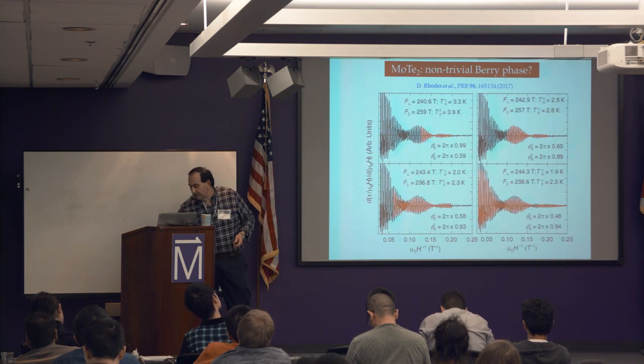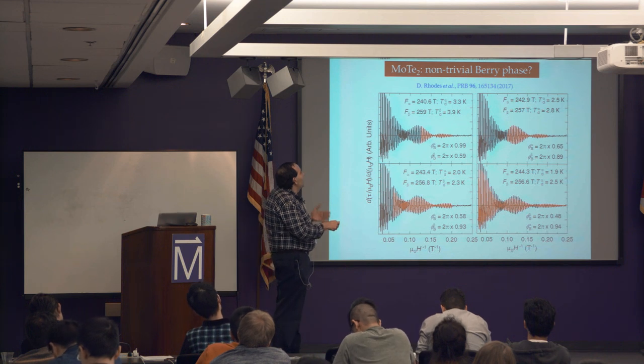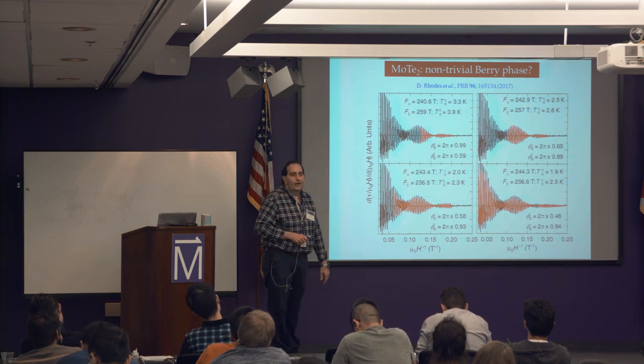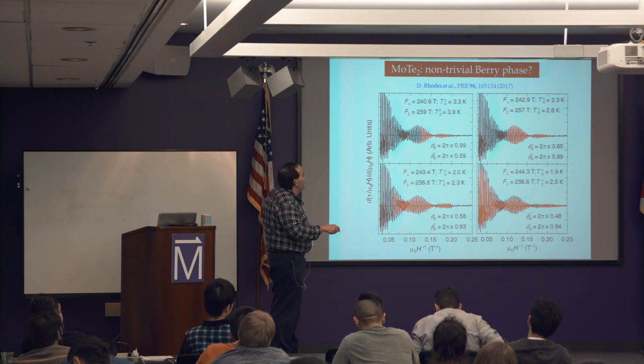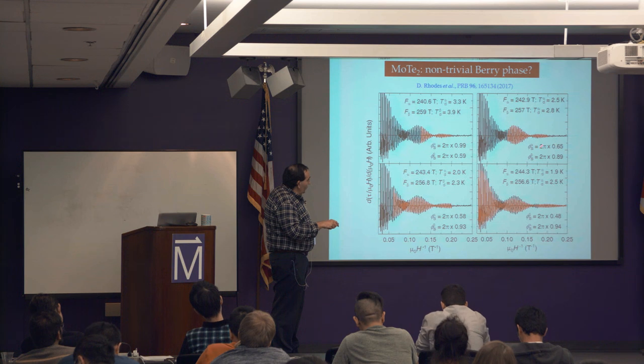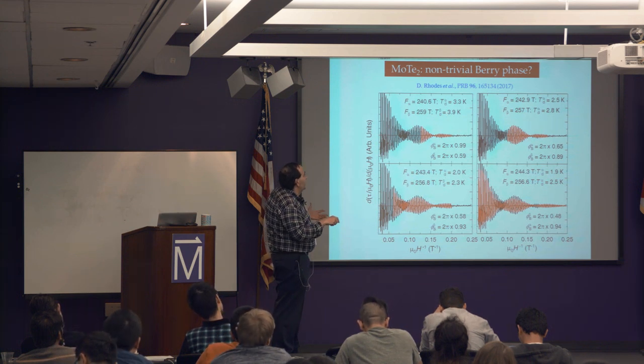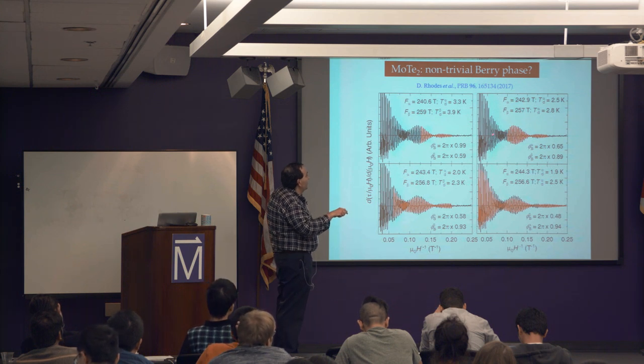I'm running out of time, and this is one of the messages I want to convey here. We try to study the Berry phase. Is this topological or not? So these are the wiggles, and these are fits to Lifshitz-Kosevich. If you take the low field part, it fits pretty well. It gives you certain frequencies, the Dingle temperatures are not too bad, and Berry phases which are not very clear as to whether they're topological or not. Change the field range, go to higher fields.